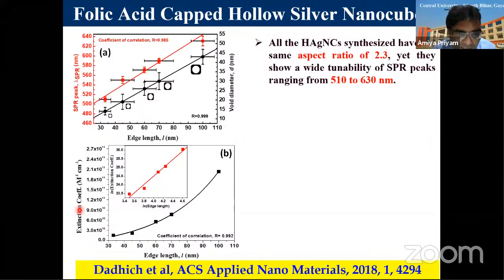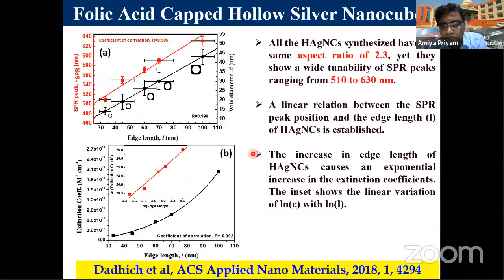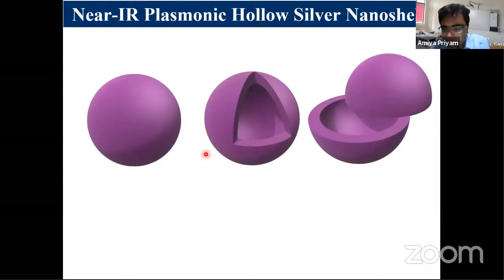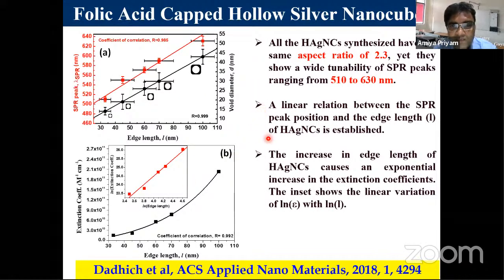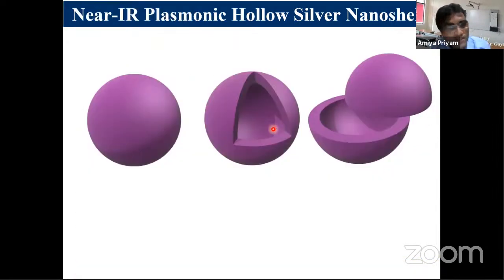We also calculated the extinction coefficient. This was a challenging task, to calculate the extinction coefficient of each of these nanocrystals. But what we noted here is that even after so much effort, we were not able to move into the near IR range. So we further strategized. Although the tunability that we achieved was the highest compared to all the other methods available, nobody working on hollow silver nanostructures has shown tunability like that, we were still not going into the near IR range, and the challenge was not yet overcome.